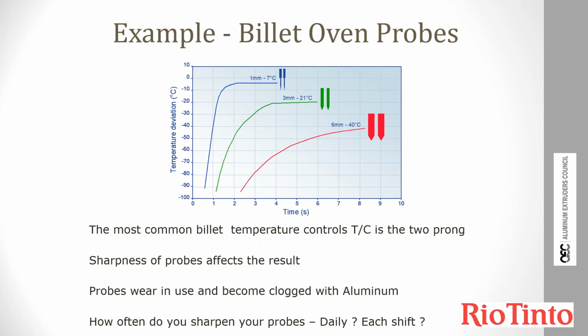And if you're only changing them once a week, I have actually seen an example where I could see the productivity of the press start to drop after about 3 days. And it would pick up again on the Monday after the probes had been sharpened at the weekend, because the billet was getting so hot that we were hitting the right-hand side of that limit diagram. So you really need to consider very much frequency of sharpening probes. For me, daily is a minimum for any extrusion plant, and each shift for automotive.